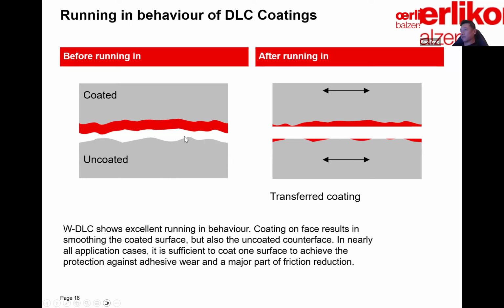But the DLC type of coating is different. We start from an engineered surface, and of course, under a microscope, no surface is perfect. You still have these peaks and valleys, and because the coating is so thin, it follows these surface contours. While the coating is breaking in against the counter surface, and also breaking itself in, it creates debris particles, which through the graphitization effect we talked about, fill up the valleys of the counter surface and form a transfer film with low friction properties. This is a different mechanism provided by DLC coatings compared with traditional contact surfaces.